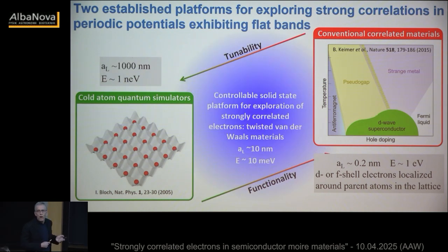And now what I'm going to try to convince you is that there is actually a third way, and this is provided by the twisted van der Waals materials, which actually have lattice length scales on the order of 10 nanometers, and then energy scales on the order of 10 millielectron volts. Okay, so which means that it's still going to be a cryogenic experiment, but in the end, this is good. It's a solid state system. So when you talk about superconductivity here, it is real superconductivity. It's not a simulation of superconductivity.